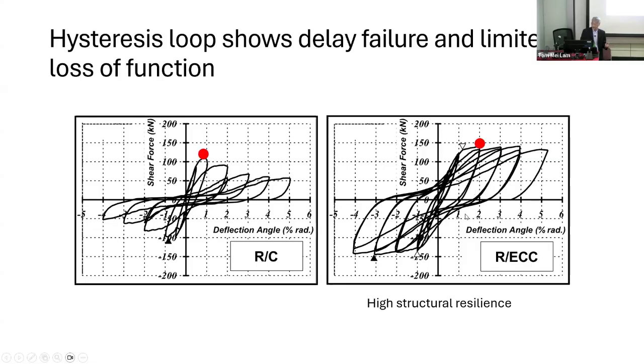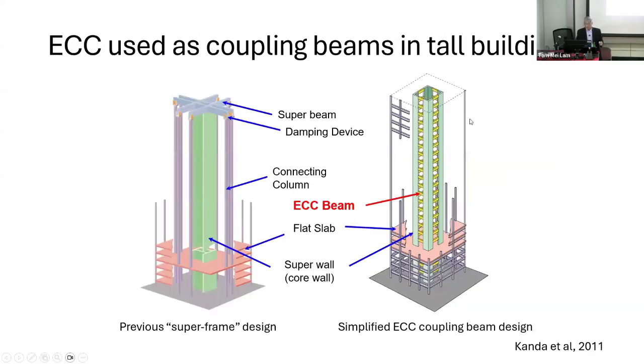And of course, energy absorption as characterized by the area under these hysteresis loops, right? Much bigger than the pinching behavior in reinforced concrete. These kinds of tests are what gave the structural engineers the confidence to actually use this ECC material in full-scale buildings. I don't mean to say it's very easy, but they were very, very careful and went through many, many different tests. And I didn't have time to show you, but they also go through fire tests and so on before they are allowed to use it.